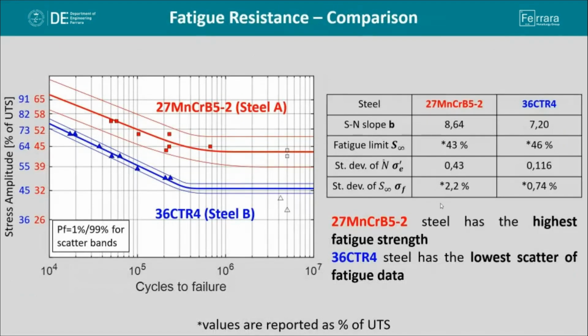So here we can see the results regarding the fatigue resistance of the investigated quenched and tempered steels, and the S-N curves are present together with the scatter bands related to the 1 and 99% probability of failure. It is evident that steel A exhibits higher fatigue strength and a higher fatigue limit with respect to steel B, but this one has the lowest scatter of fatigue data. And for reasons of intellectual property, data were normalized and reported as a percentage of ultimate tensile strength in terms of stress amplitude.